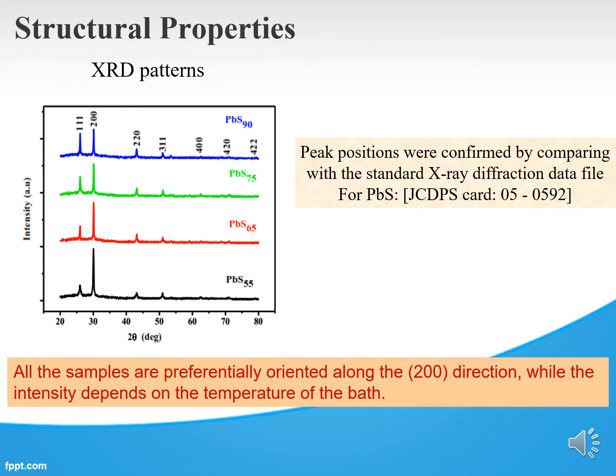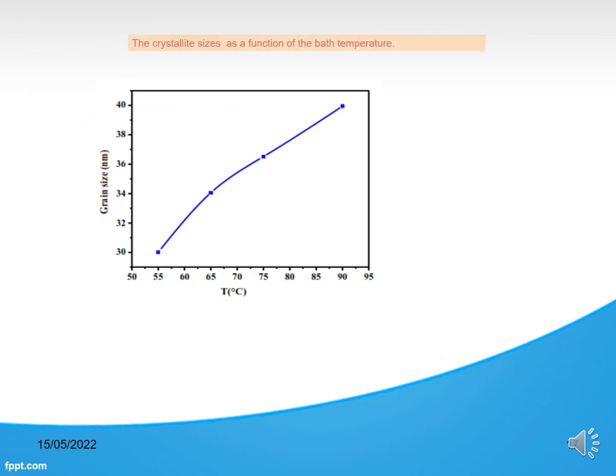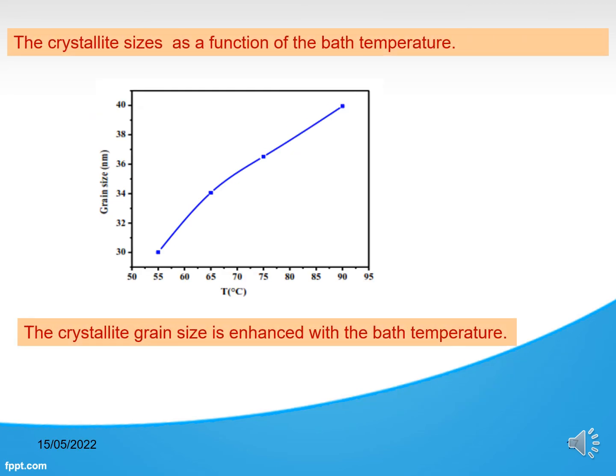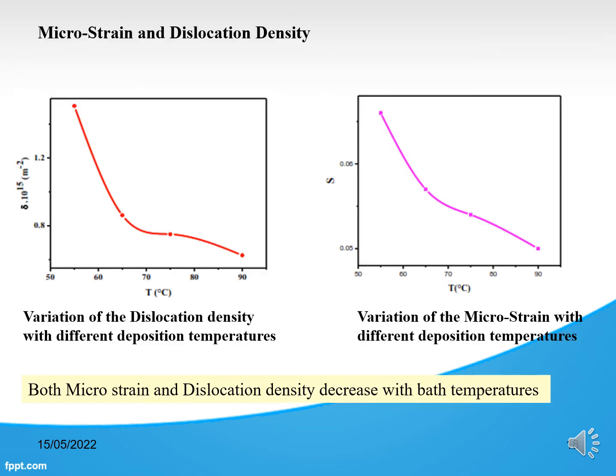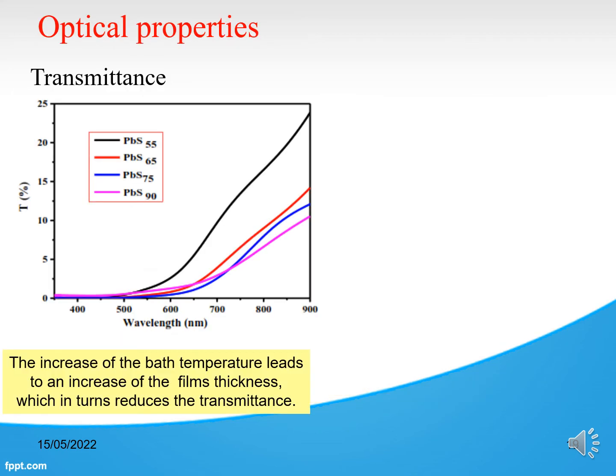Structural properties. The XRD patterns. All the samples are preferentially oriented along the 200 direction, while the intensity depends on the temperature of the bath. The crystallite sizes as a function of the bath temperature. The crystallite grain size is enhanced with the bath temperature. Microstrain and dislocation density. We see that both microstrain and dislocation density decrease with bath temperature.